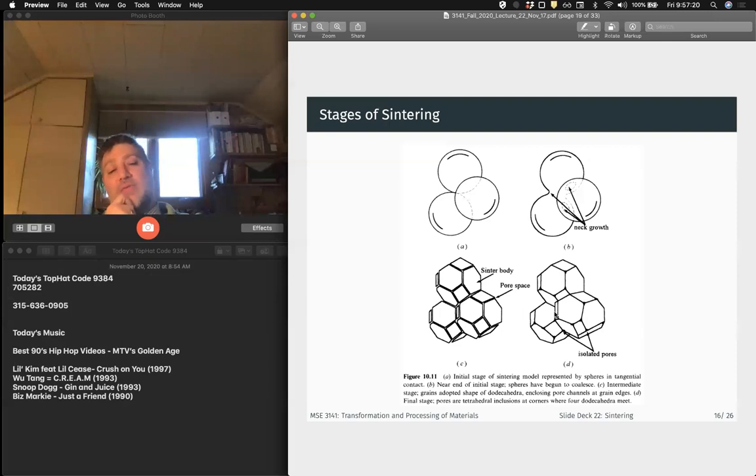And then we start to get really significant grain growth, right? So remember, why would the presence of these channel pores inhibit the grain growth? It's an energy thing, right? If this grain grows, our pore has to move from a triple line where there's lots of free volume to the inside of a grain, right? And that's just an energetically unfavorable situation.